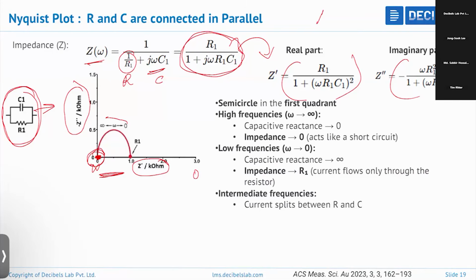At higher frequency, the capacitive reactance is 0. When you apply a high frequency, the capacitor acts like a short circuit, so there will not be any capacitor. The electron can easily move, and it will not experience any resistance because there is a path for the electron to move in this direction. So the impedance is 0. There is no resistance at high frequencies.